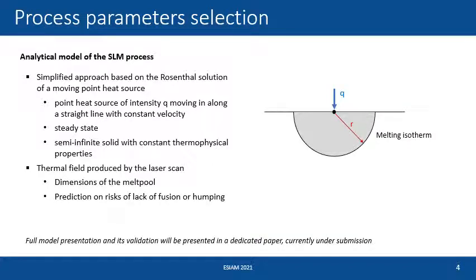The adopted process parameters were selected on the base of an analytical model of the selective laser melting process. It's a simplified approach that is based on the Rosenthal solution of a moving point heat source, namely a point heat source that moves along a straight line with constant velocity. We focus on the steady state phenomenon, and we consider a semi-infinite solid with constant thermophysical properties. So we make some assumptions to simplify the analysis of the process, but trying to keep only the information that we need to try to develop a feasible region of the process.